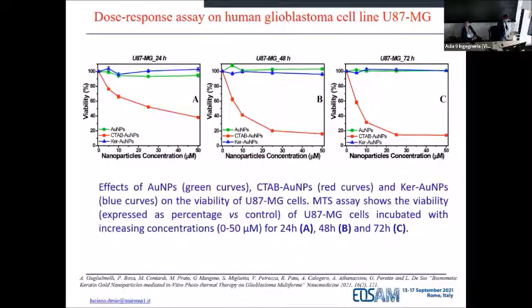And as a comparison, here you have the citrate-capped golden nanoparticles. Of course, they are highly biocompatible, but we cannot work with them because the stability is very low. Those particles are not very useful for real applications. That's why the comparison is between our particles and the CTAB-capped golden nanoparticles, and you can see that there is no comparison. To begin with, we decided to work with a very aggressive form of cancer, which is glioblastoma. This is a brain cancer. That's why we decided to work with something which is very challenging right now.